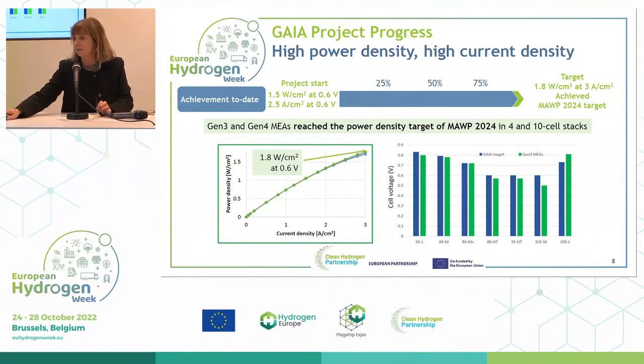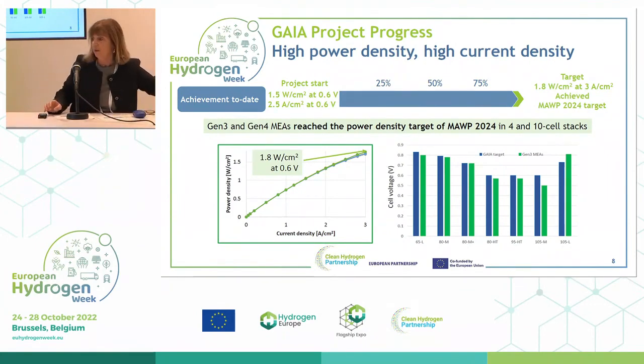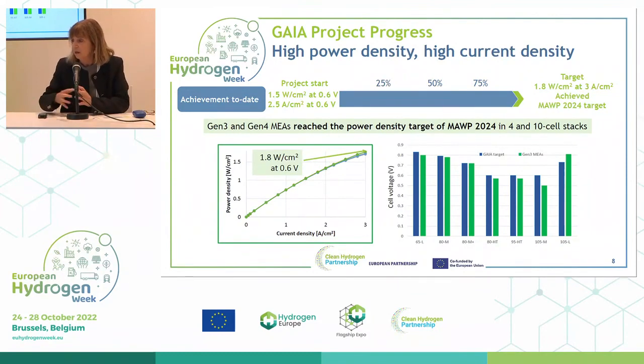And so what we obtained in terms of the project progress was shown the other day, I think, by Lionel yesterday perhaps. This is showing that we managed to achieve the 1.8 watts per square centimetre at 0.6 volts. Very satisfactory result. It corresponds, as it says up there, to the power density target of the multi-annual working plan for 2024, so that's an important result.